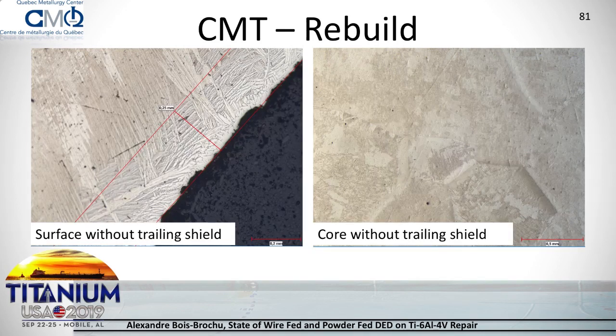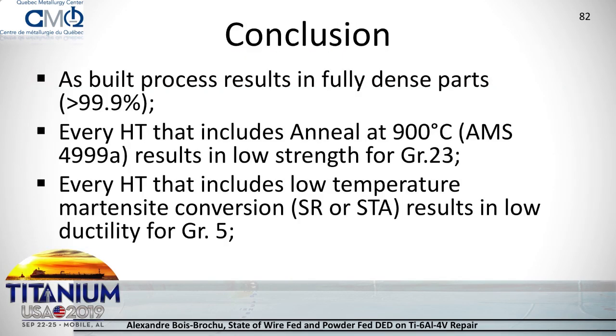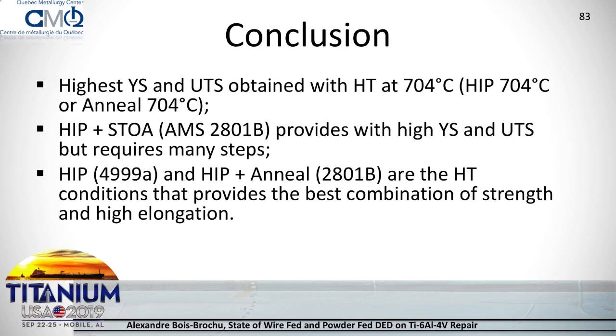So in conclusion, the as-built process for powder DED produces fully dense parts. Every treatment that ends with an annealing at 900 Celsius results in low strength for grade 23. Meanwhile, every treatment that uses a low temperature martensite conversion results in low ductility for grade 5. The highest yield strength and UTS combination is usually with the heat treatment with 704 as the final heat treatment, actually the only one, so either HIP at 704 or anneal at 704.